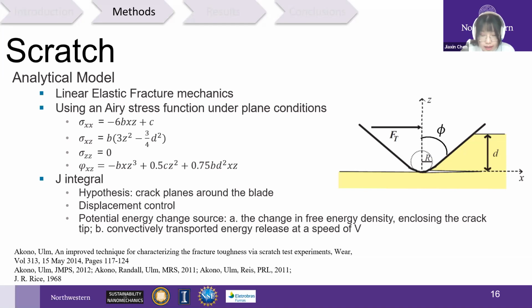Consider a scratch test in a linear elastic brittle material with a crack emanating from the tip of the probe. We can then evaluate the rate of change in potential energy in a material volume surrounding the crack from the perspective of an observer that moves along that crack. This leads to applying the famous J integral to calculate the energy release rate, knowing the stress and strain distributions ahead of the probe.